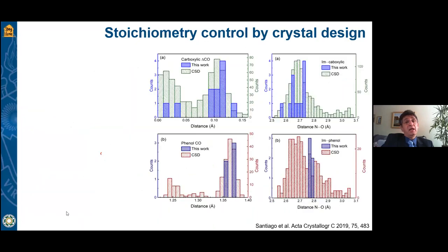If you notice, at no moment did I talk about co-crystals or salts. In fact, the definition between co-crystal and salt can be difficult. There are some cases where they are well defined. There is a thing called the salt-co-crystal continuum. And in fact, we analyzed our structures compared with the CSD database, comparing some different parameters from our synthon strategy. In the case of, for example, the phenol groups, we compared the distance between the phenol, the imidazole group and the phenol compared to the database.